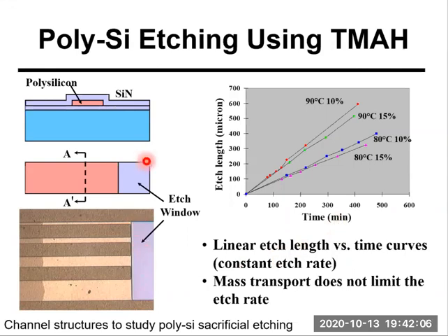To study polysilicon sacrificial etching in TMAH, long strips of polysilicon were encapsulated inside the silicon nitride channels. Again, we use silicon nitride microchannels. Then the channels were opened at one end, the right end. And the chip was immersed in TMAH solution. So the polysilicon will be etched by TMAH, starting from this opening.